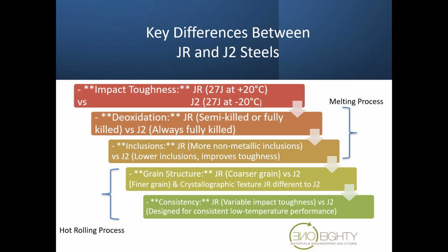So it's tied up in 2 things. This impact toughness of 27 joules at 20 degrees and at -20 degrees is tied up in the melting process and the hot rolling process. In the melting process, it is the deoxidation process that is used when they are melting the steel and melting the ore, as well as the control of the amounts of inclusions, which is kind of related to the deoxidation process.